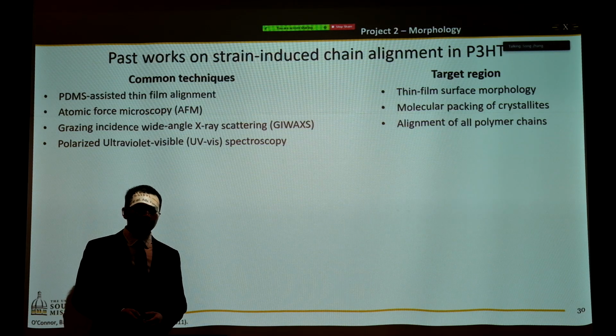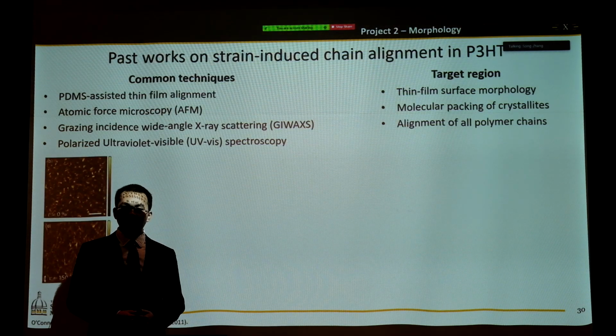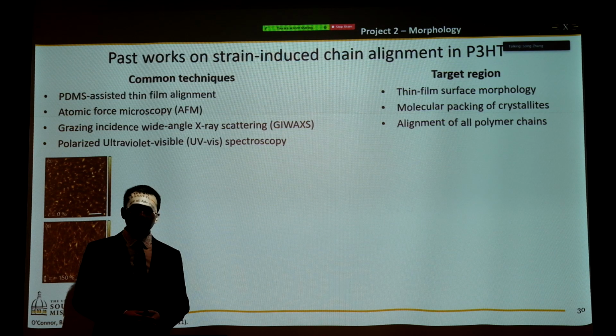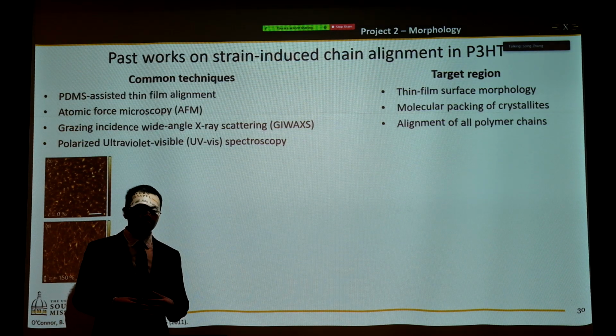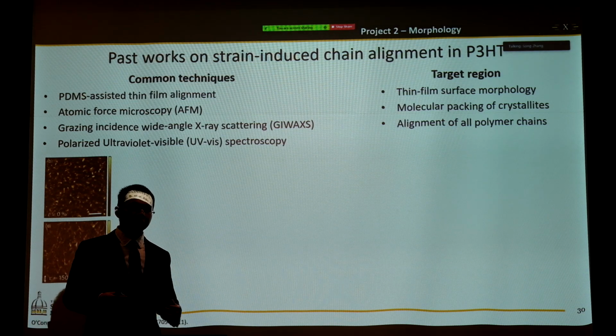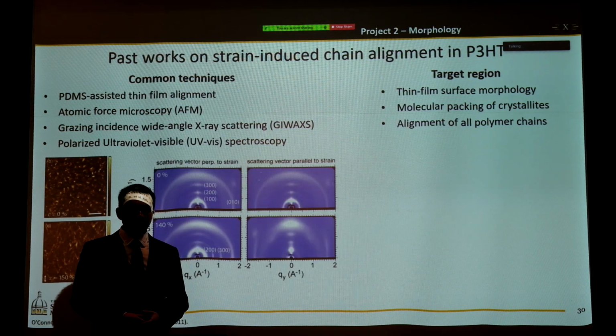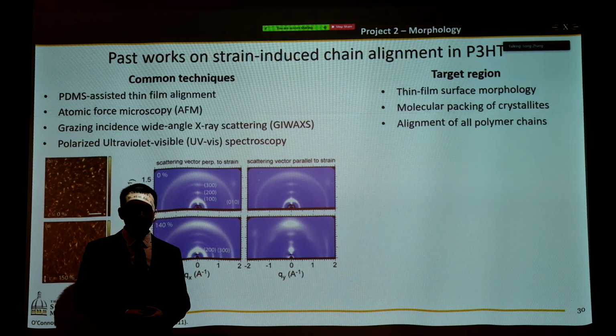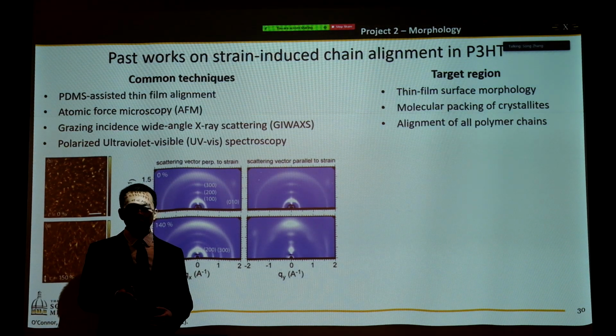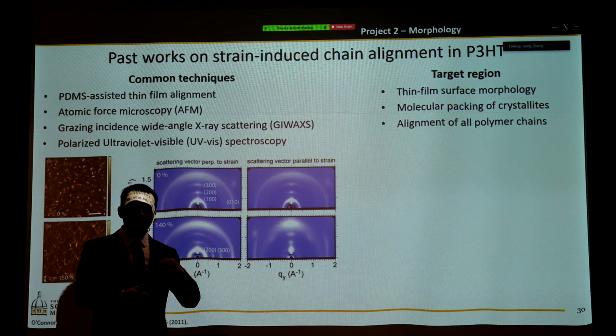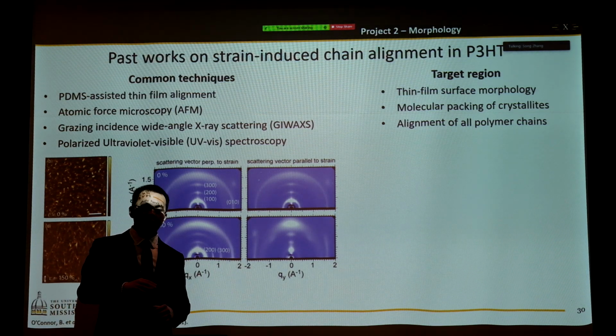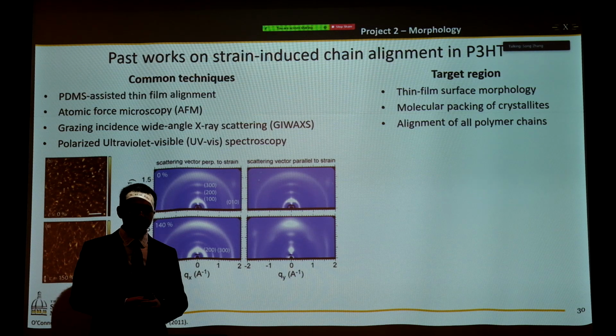By using AFM, they can look at the thin film surface morphology. As seen in the bottom left, you can see that thin film morphology will be different from 0% strain to 150% strain. Basically, it's more elongated. And by using GIWAXS, we can look at molecular packing of crystallites. If we choose different angles between the incident X-ray and the polymer aligned thin film, we will be able to understand how the crystallite is aligned along different directions.